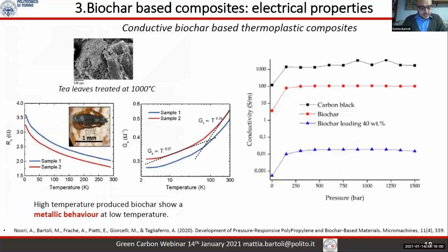But a further step was the comparison between biochar and carbon black, and also in this case, you can see that only biochar composites display a good conductivity in these measurements, even if neat, pristine carbon black has a native conductivity higher than the biochar used in this case, tea leaves treated at 1000 degrees. In this case, it's quite a high temperature, but as you can see from the graph on the left, biochar shows a conductive behavior close to a metal.